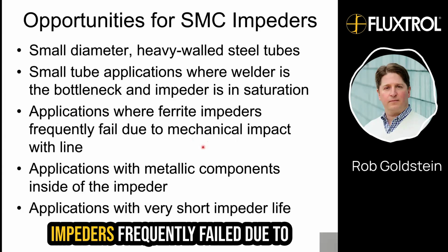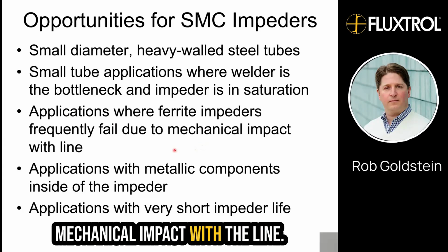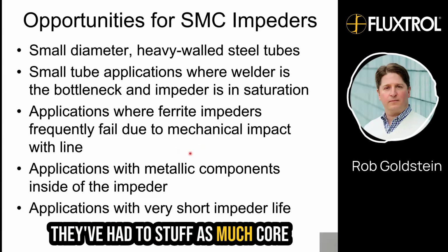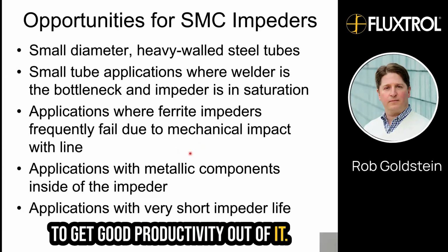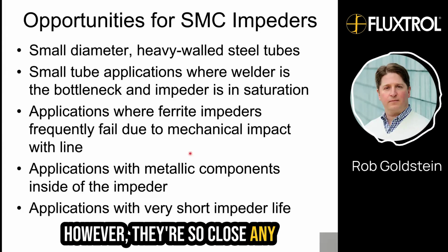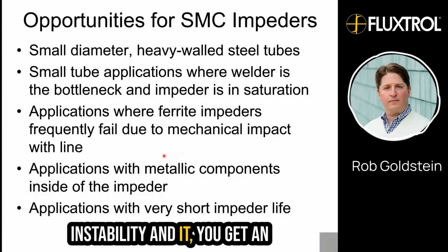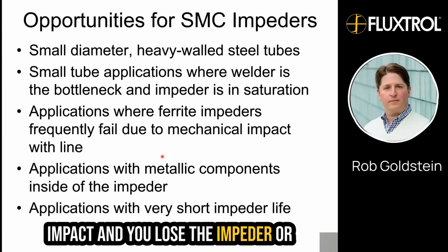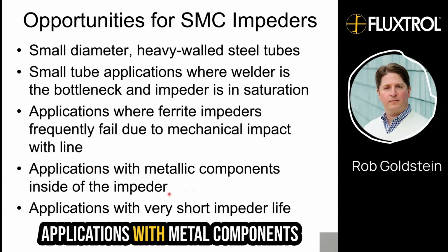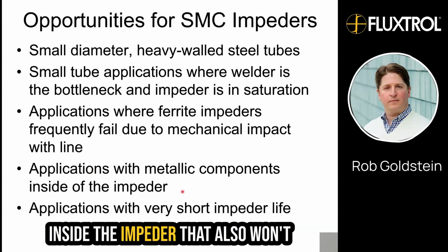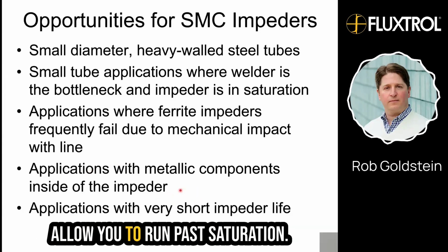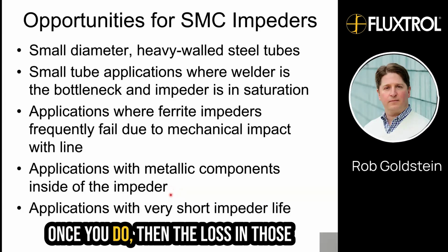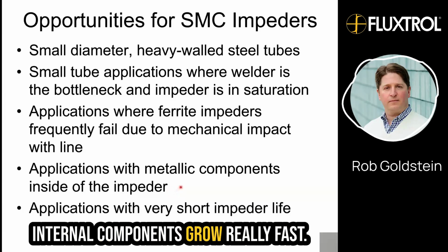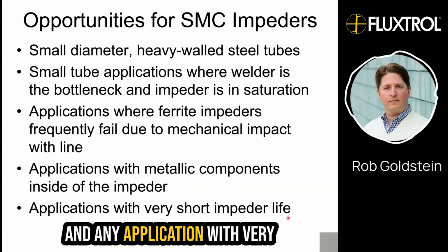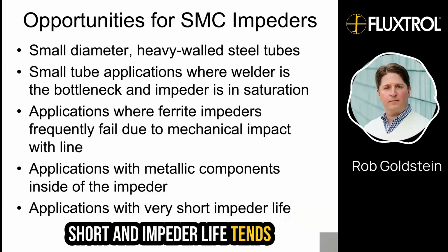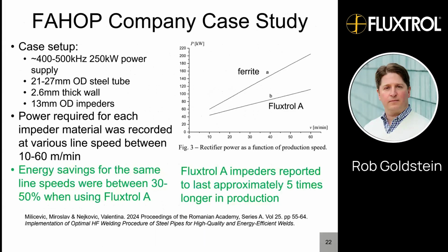Applications where ferrite impeders frequently fail due to mechanical impact with the line. They've had to stuff in as much core to get good productivity out of it. However, they're so close, any instability and you get an impact and you lose the impeder. Or applications with metallic components inside the impeder that also won't allow you to run past saturation, because once you do, the loss in those internal components grows really fast. And any application with very short impeder life tends to seem to be a candidate.